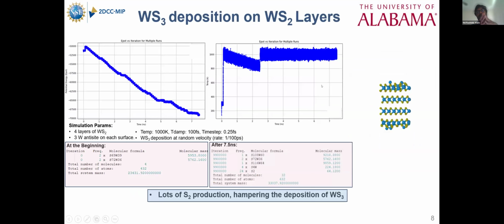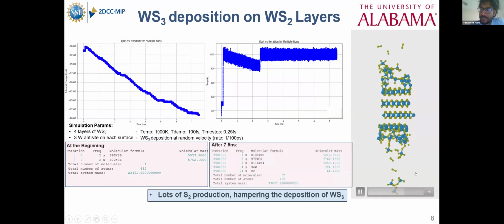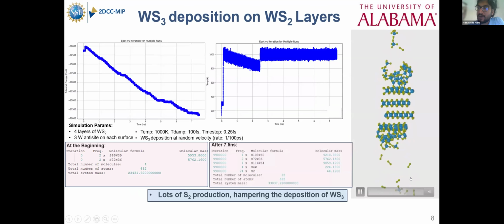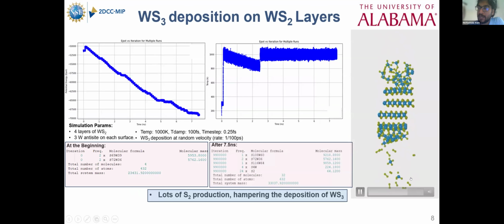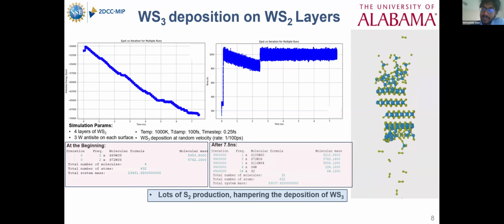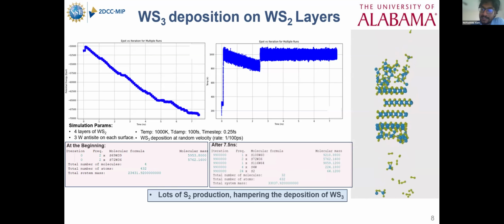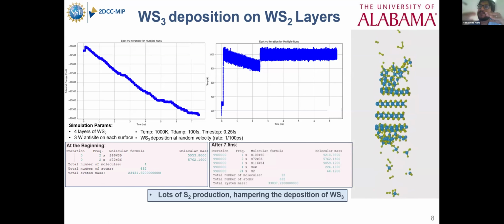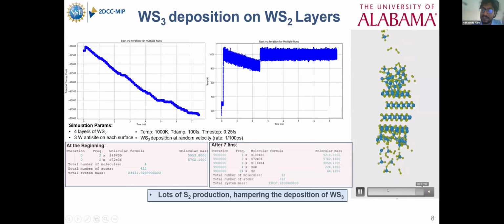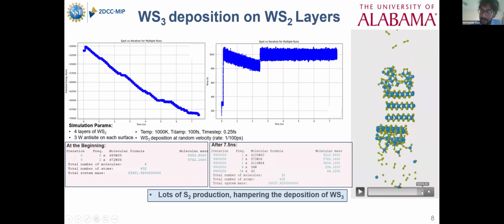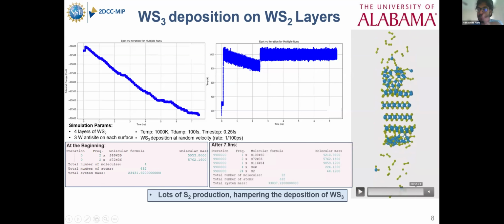In the next case study, we did some depositions of tungsten trisulfide on a tungsten disulfide layer. We can see from this curve that we added tungsten trisulfide on top of the tungsten disulfide layers. Our expectation was that we would see nice monolayer growth on top of the substrate, but instead we saw cluster-like structures and a lot of S2 gases flying over the vacuum.